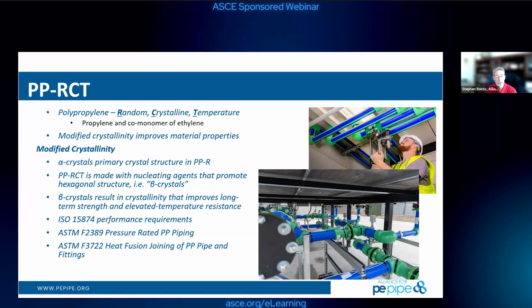And then this newer technology came up, I don't know, maybe 10 or 15 years ago, maybe a little bit longer, that changed the crystallinity into what we call the beta phase or a hexagonal phase, to give more of that type of crystallinity. And what they found is that it really increases the strength and the temperature resistance of polypropylene. So that opened a whole new realm of being able to use these materials in a lot of HVAC applications. It lends itself perfectly for these data center environments where the temperatures have to get up to 200, maybe as high as 230 degrees Fahrenheit in these applications.